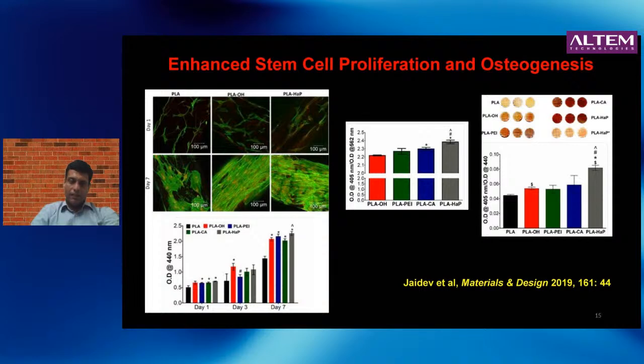However, by day 7, you can see that the cells are growing on the as printed scaffold, but not so well. Whereas when we have hydroxyapatite on it, you can see that the scaffold is completely covered with these stem cells. And you can quantify them with various assays. And what this tells you is that, yes, indeed, having the hydroxyapatite coating seems to help compared to the as printed scaffold. However, the other important thing, aside from growth of the cells, is the ability of the stem cells to turn into bone-like cells.